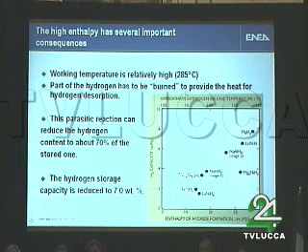Part of the hydrogen has to be burned to allow other hydrogen to desorb, and the parasitic reaction can reduce the hydrogen content to about 70%, and so only about 7% of hydrogen can be stored in lithium nitride. And so it means that it could meet short-term DOE goals, but not long-term goals.